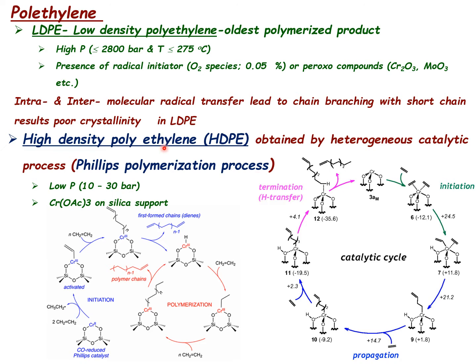The Phillips company developed a catalyst called the Phillips polymerization process, based on chromium acetate on silica support. The silica support has Si-OH bonds; the chromium acetate interacts with these, and the chromium becomes anchored on the silica surface — the acetate ligands leave and chromium is anchored through Si-O-Cr bonds. This chromium-anchored species acts as the polymerization catalyst. The olefin coordinates at the chromium center, and chain propagation proceeds, forming a chromium-hydride species and then a polymeric chain.